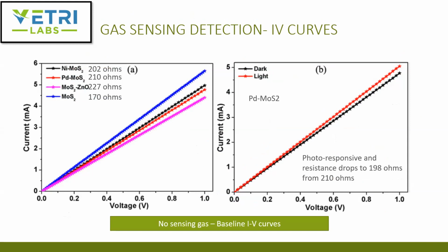And these are the resistance values. The nickel molysulfide is about 202 ohms, the molysulfide 210, with the zinc oxide slightly higher. Molysulfide itself, as a pure material, is 170 ohms. Some of these are photoreceptive. This one, particularly the palladium doped molysulfide, is photoresistive and photoresponsive, I should say, and the resistance does drop when you turn on the light.